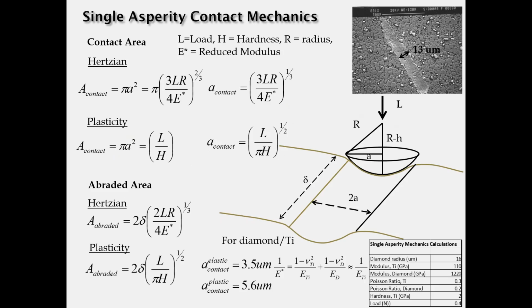In the single asperity example of mechanically assisted corrosion, we can do more contact mechanics analyses to better understand the interaction. Work we did in the late 90s, early 2000s used high-speed single asperity scratch tests with a diamond tip. You can see a damaged scratch that was induced by one of these tips. We can measure very accurately the area of that abrasion, the diameter, the length, and understand something about the area abraded as it relates to the hardness of this alloy and to the force applied to that indenter.